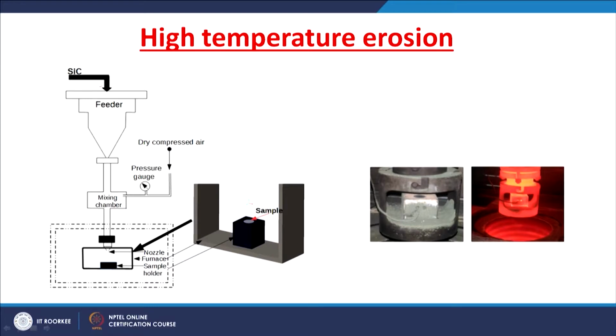So, with this information, we conducted the high temperature erosion test. The high temperature erosion test was done using a high temperature particle erosion tester. Silicon carbide particles, which we call erodents, of around 40 to 50 micrometer particle size were mixed with air, and then this mixture was used to erode the surface of the composite. We can see the real time photograph of this material when it was at a high temperature of around 800 Celsius.